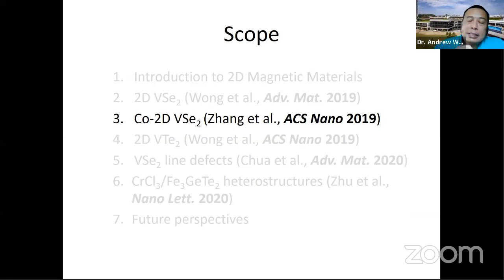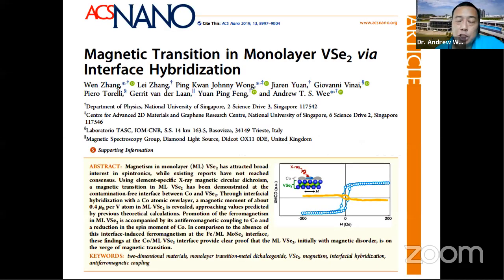Next, we studied this system, but by depositing cobalt on top of it, which is a ferromagnetic metal. We wanted to see whether we can make vanadium diselenide magnetic via an interface hybridization effect using cobalt ferromagnetic metal. So we used mainly XMCD because, again, as I said, this gives element-specific information on magnetism. And so we could this time see the hysteresis as shown in this table of contents figure.